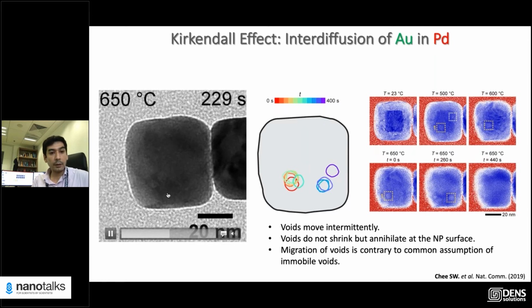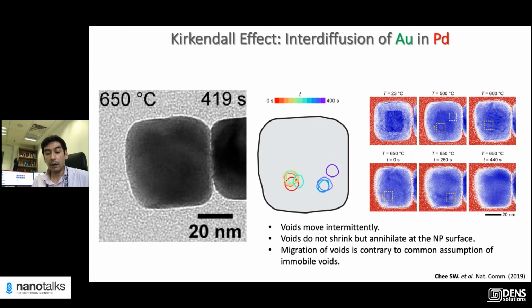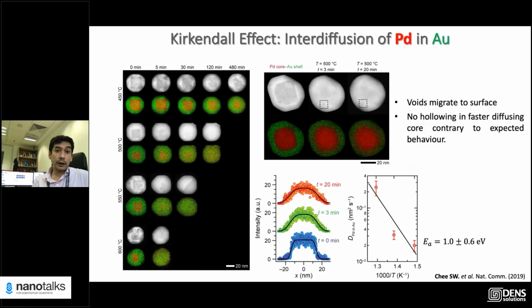They can get intermittently pinned, but they eventually disappear or annihilate once they reach the surface of the overall nanoparticle. So that was gold in palladium. You can do the same thing with palladium in gold. So you reverse the geometry: we put the palladium in the center and the gold outside, and then you can measure the diffusion for the palladium.